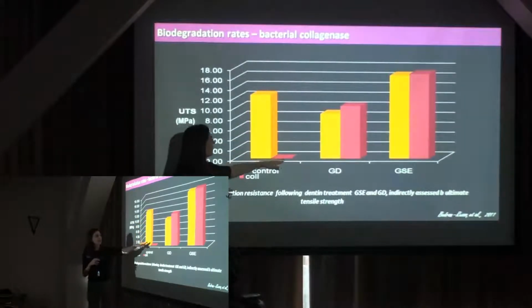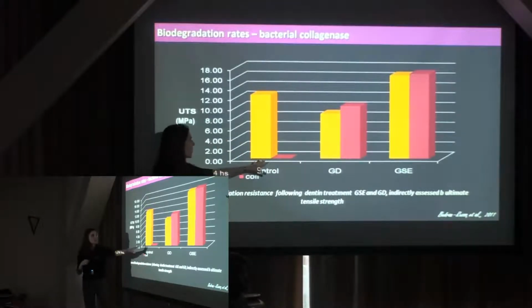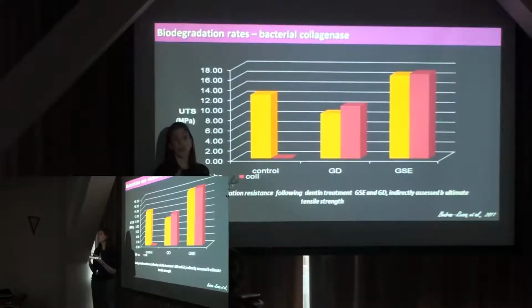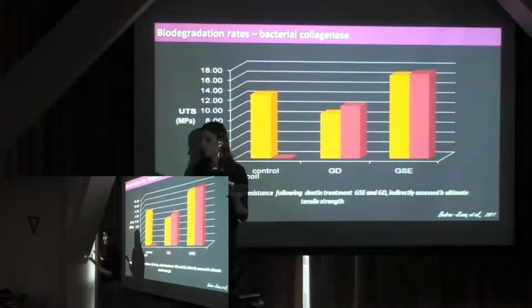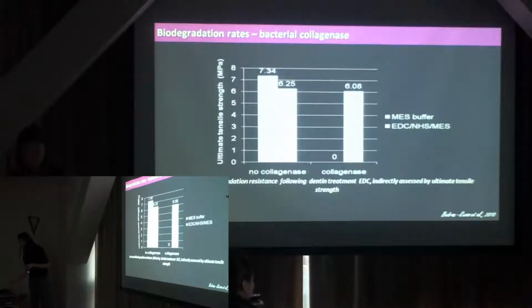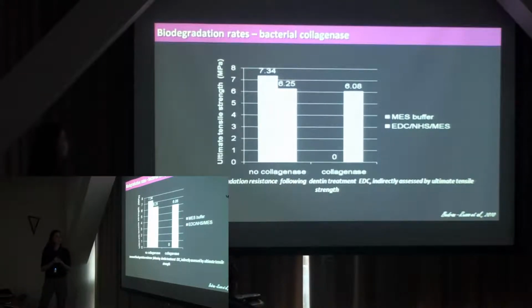So we had samples that we broke right after the test, and then samples that we put in collagenase, and then we break them. What we notice is that our controls are fully degraded, so there's not even a sample there to test. While our treatments, regardless of the treatment, you're able to test. So it gives us this indirect assessment showing the decrease in biodegradation. The same is true here. This is just for the EDC.